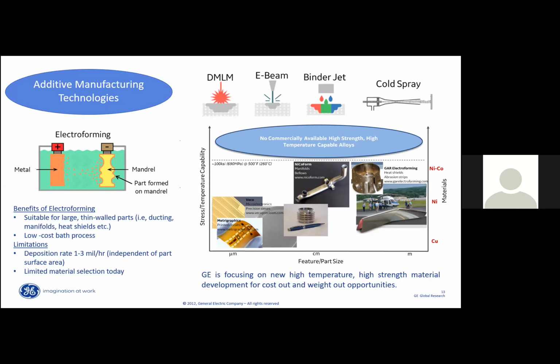But by moving over to electroforming, we can basically reduce those steps to 4. So you print the mandrel, you electroplate it, and then you remove the mandrel. And I say 4 because sometimes you might need to do a little post-processing, but most of the times the electroforming part is good as it is. You can use it straight out of the box.